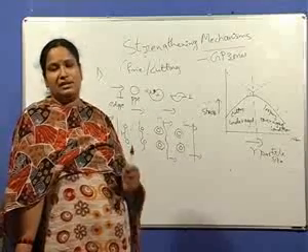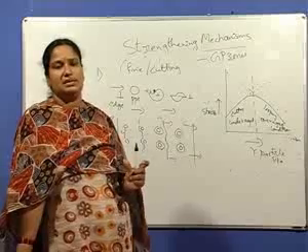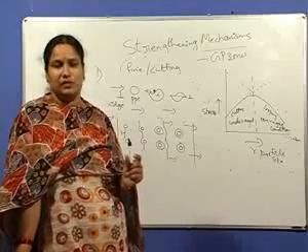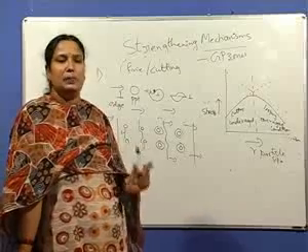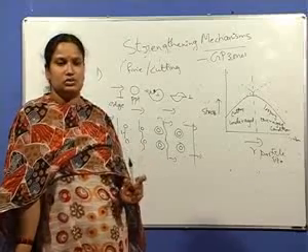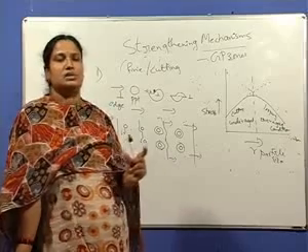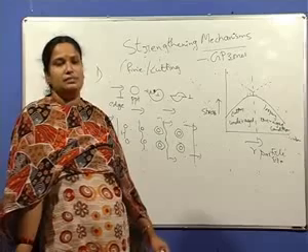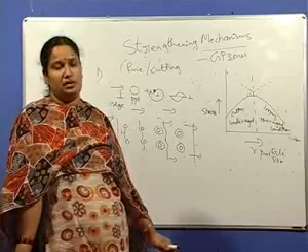The two mechanisms that operate are the cutting mechanism, where the dislocation cuts the precipitate particle when it is very, very fine, and the looping mechanism, when the precipitate is coarse, where the dislocation bends around the precipitate to bypass it. That looping mechanism is also known as the Orowan looping mechanism.